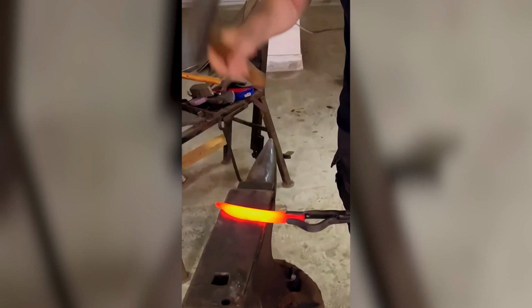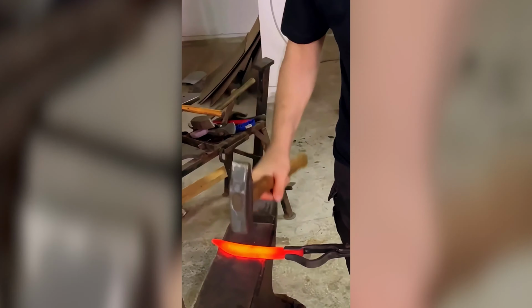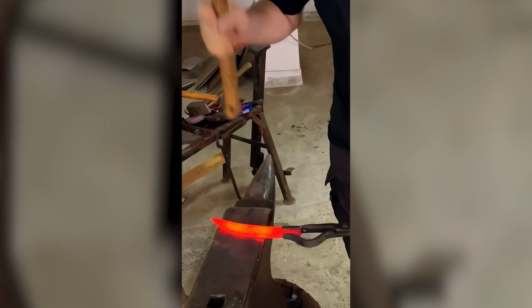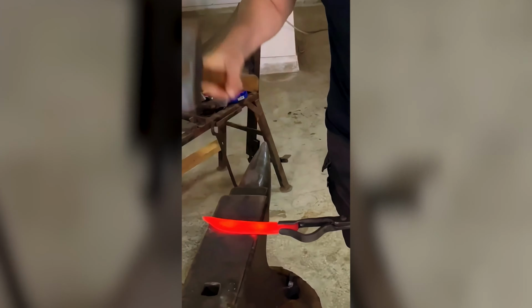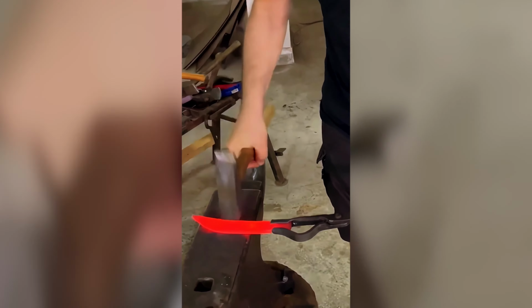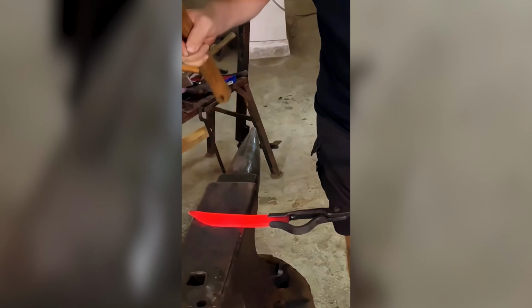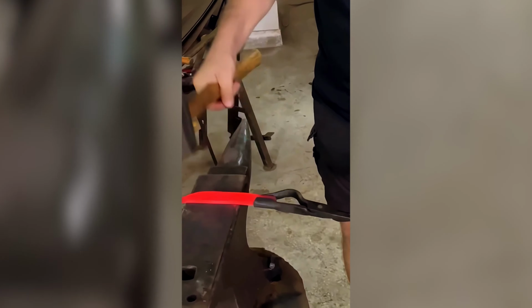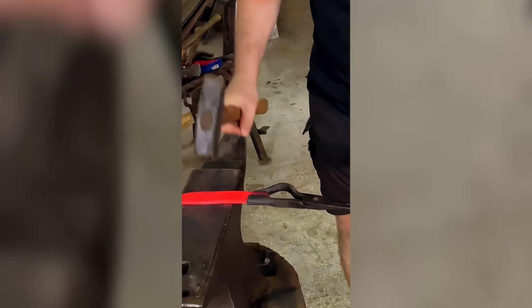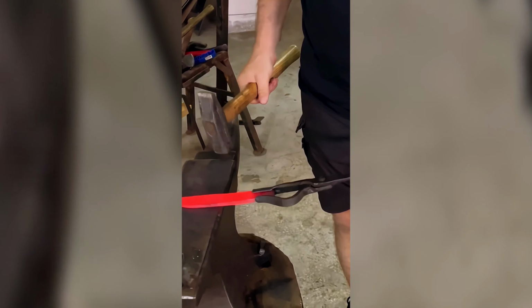The first hammer blows have a broad striking surface. These blows are for mass distribution. The goal is not to lengthen the steel. It is to move material to the correct locations. An incorrect blow at this stage disrupts fiber orientation. This disruption later becomes a fracture initiation point.